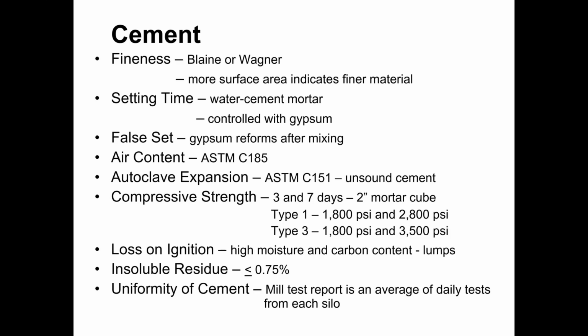Loss on ignition, we talked about this test with regard to fly ash. When used with fly ash, it's an indicator of the carbon content, but it can also be used with cement as an indicator of the moisture content. The higher the moisture content of the cement, the more of a concern that is. The cement reacts with moisture, and so the more moisture that's available in the same environment as the cement, the greater the likelihood that the cement will react prior to when we want it to react, which is after it's been combined with water and other materials in our mixer.